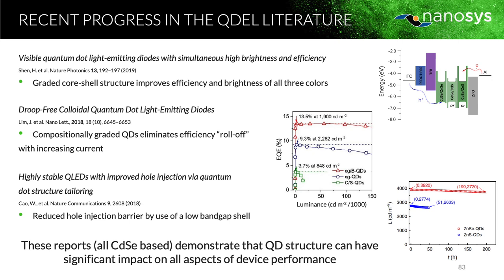All three of these groups made these advancements by altering the structure of the quantum dot. And to not go into incredible detail, the way that I would probably summarize it most generally is that they all took careful control of the radial profile of the elements from the center of the quantum dot to the outside. And if you think about something that's only some nanometers thick, that's actually tricky to do. But that's the level of control that you need to make these types of high-performing materials.